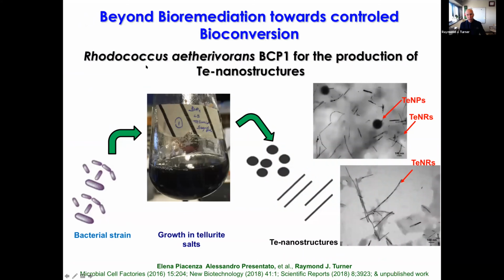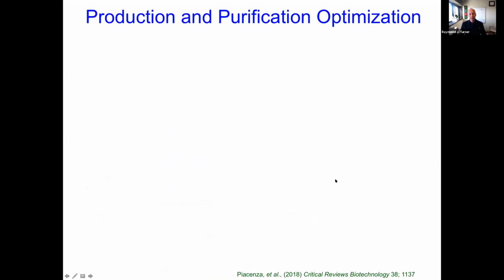So we chose this organism, again, BCP1. It's a pretty robust organism. And when it's stressed, it produces natural surfactants, which allows us to trick it to generate either nanoparticles or nanorods as the end structures. This gives the difference between three-dimensional growth and one-dimensional growth, because you'd have the rod covered by the biosurfactants, so the atoms are only being added to the one end.